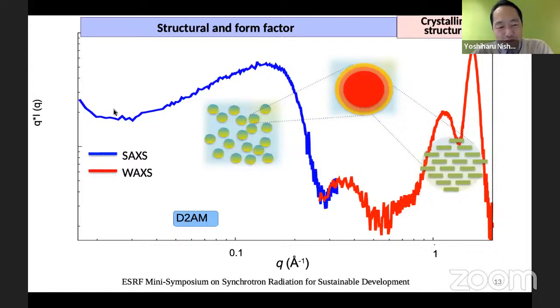Because in the horizontal axis we have the scattering vector, which is reciprocal, it corresponds to roughly the reciprocal of the structural details. If you go to the higher scattering vector, you go to the smaller details. So we see what happens at the crystalline structure level. And at the smaller Q, we see the packing and the form factor of the object inside the matrix.